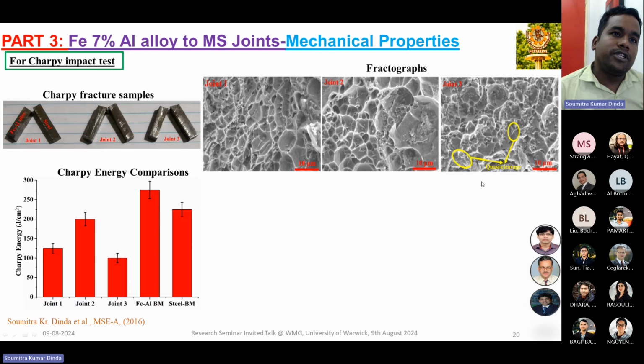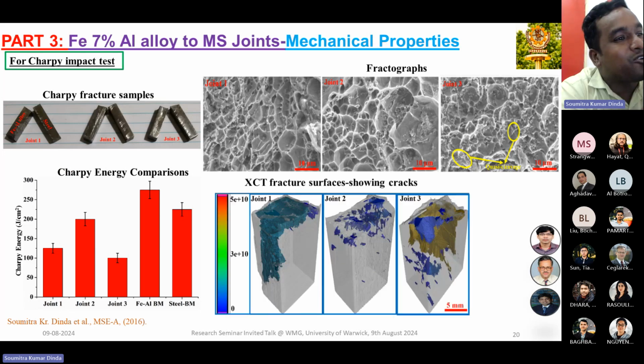So joint 1 and joint 2 show the dimple type of fracture. But in case of joint 3, we saw quasi-cleavage, that means towards the brittle mode of fracture. And most interestingly, we did one more thing, that is the X-ray tomography for the whole sample, for one side, definitely one side. We are taking the Fe 7% aluminum alloy side to see how the cracks look.